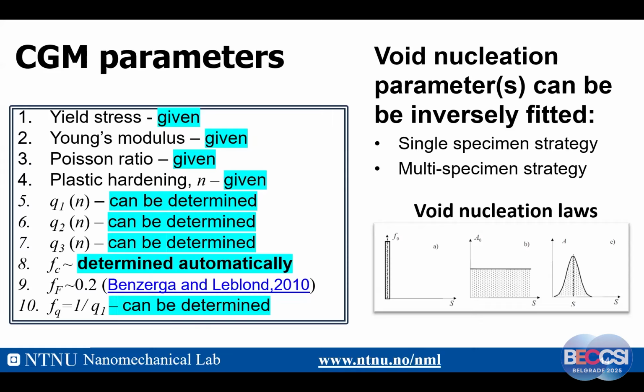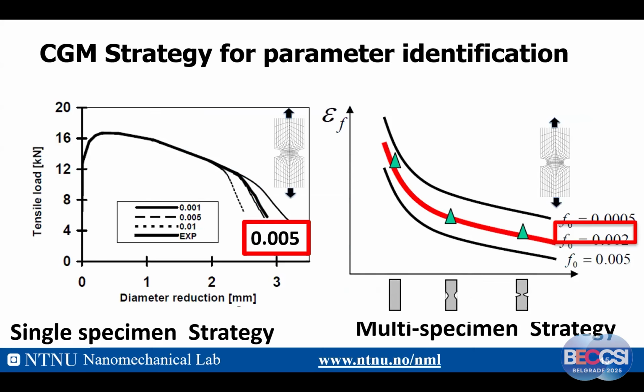So we can use a single specimen strategy or a multi-specimen strategy to fit the nucleation parameter. Because the nucleation parameter is the only parameter which needs to be determined, it links to the material failure by a one-to-one relation. So here are the strategies to fit. If we use one single specimen, then we can, for example, make different calculations with different initial void volume fractions.